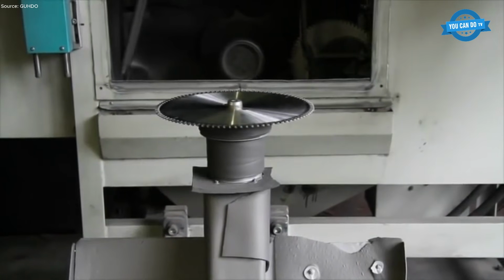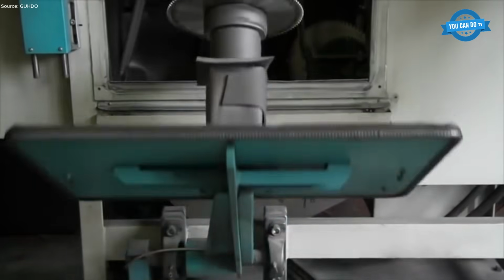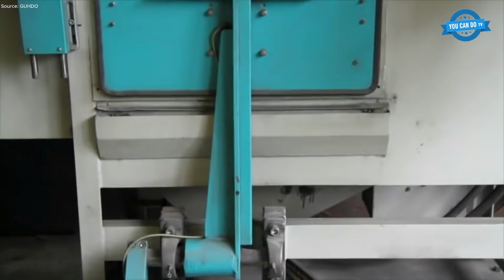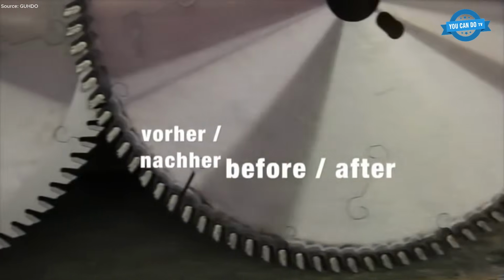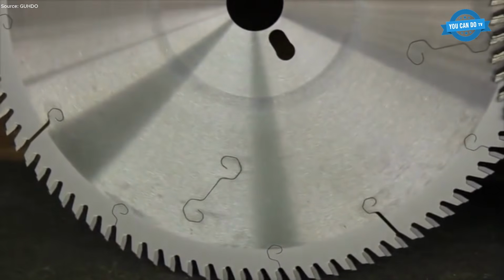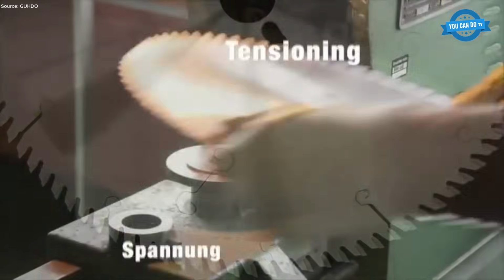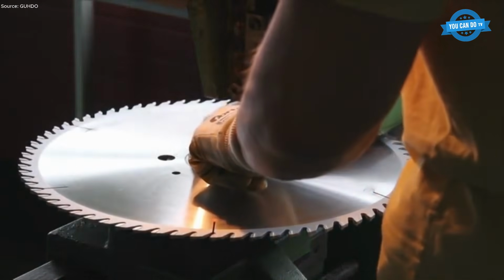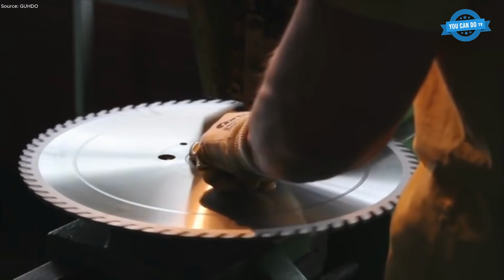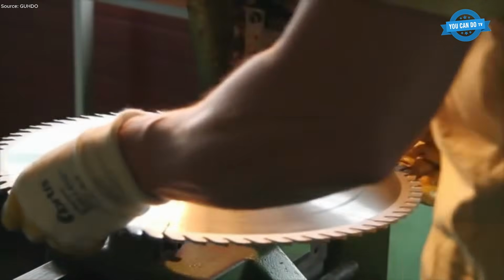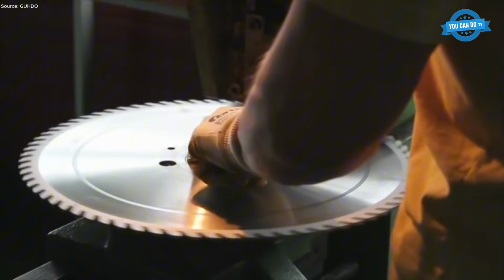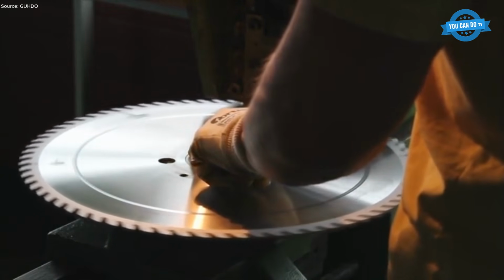After brazing, sandblasting cleans the surface and prepares it for further processing. The blade then undergoes tensioning, a critical step where internal stresses are intentionally adjusted. Proper tensioning ensures the blade remains flat and stable during rotation, even under thermal load. Straightening follows, correcting any residual distortions to achieve perfect flatness.